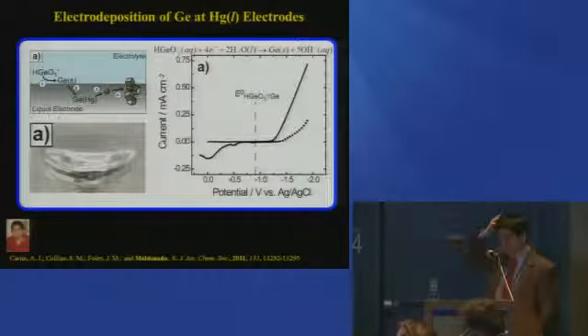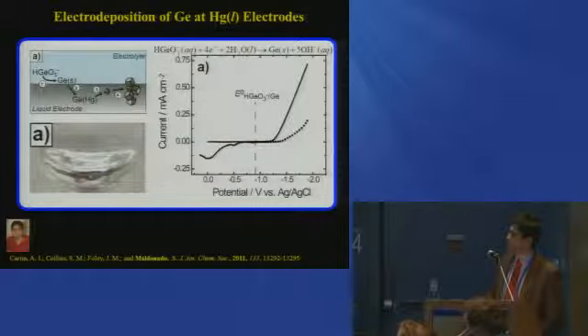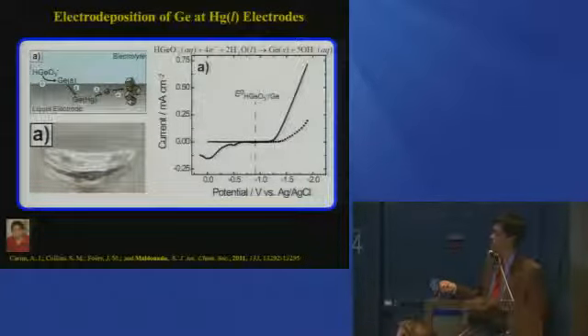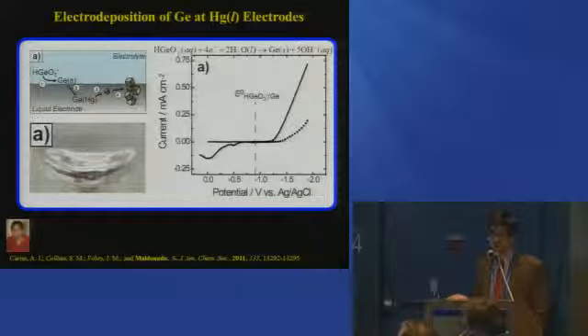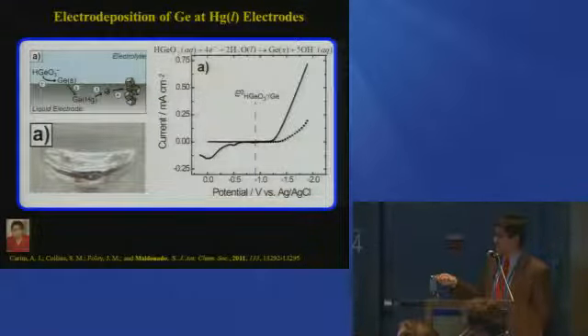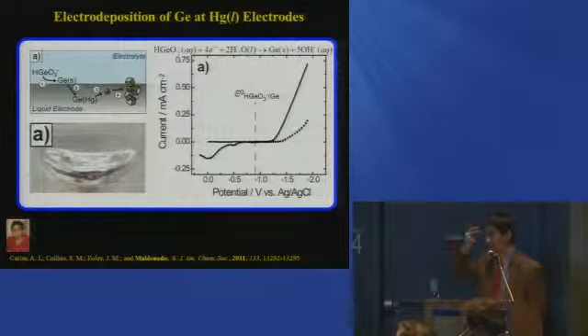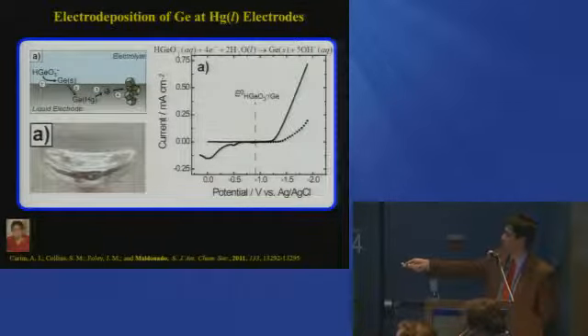This is what it looked like in the first generation. Sort of the simplest idea, which again goes back to our roots, is to use a mercury cathode. This is a mercury pool electrode on the bottom of a beaker. This is in an aqueous solution in the absence of anything besides some background salt and some buffer to make it a slightly alkaline pH. A mercury electrode is pretty inert towards evolving hydrogen, so you have a really nice cathodic window, and that's what this dotted line here is.